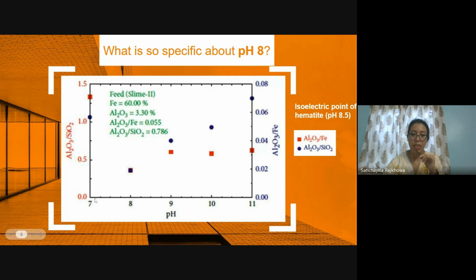And from this study, if we study different pHs, and if we study the alumina silica ratio and alumina iron ratio, then this is the lowest ratio we can get at this particular pH. And to get better or more iron from iron ores, the ratio has to be around 0.05 for alumina iron ratio, and for alumina silica it has to be less than 1.